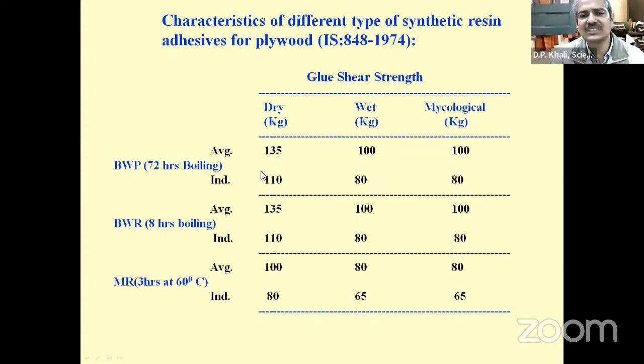Out of those 6 samples, none should have less than 110 kg. How much area should withstand this load? Only 1 square inch should be able to withstand more than 135 kg. Similarly, in the case of BWP as well. And in the case of MR, because it is being used for interior purposes, 100 kg only, individual 80 kg.